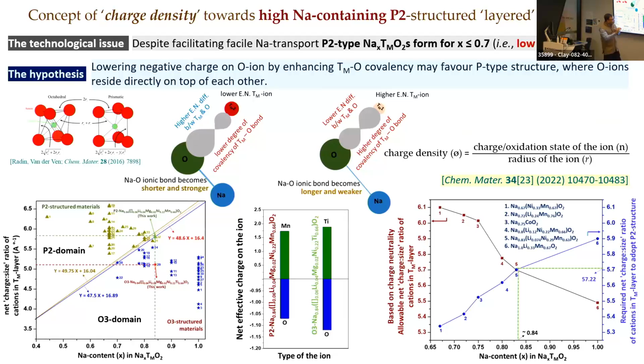So then there will be a compromise based on the required charge to size ratio for adopting the P2 type structure, and the allowable charge to size ratio based on the charge neutrality. So while trying to design compositions, one will all face this compromise, and one will narrow down to a particular composition which seems feasible. So this is where we were for this material, and as I will show here,